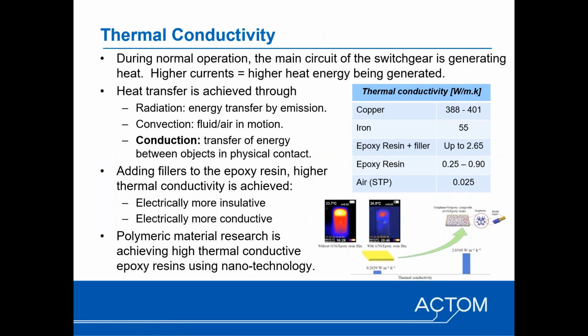One of the other components, and Narek touched on this, is the thermal conductivity of the epoxy. Not only does it need to deal with the electrical stress, you also need to deal with the thermal stress of the material. During normal currents, the higher the currents, the more heat is being generated, and the epoxy needs to be able to get rid of that heat in order to still maintain the rated current. Heat transfer can be done as a combination of 3 methods. The first one is radiation, where the heat energy transfer is done by emission. Convection, where airflow or fluid flow in motion is basically getting rid of the heat energy. But in the case of solid dielectrics, conduction is the dominant means of energy transfer.